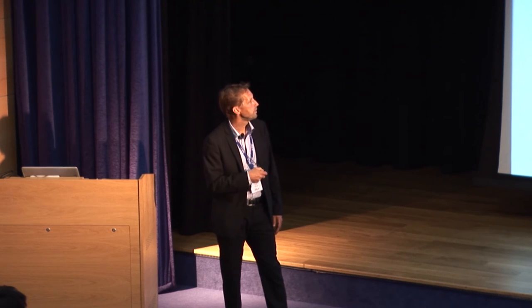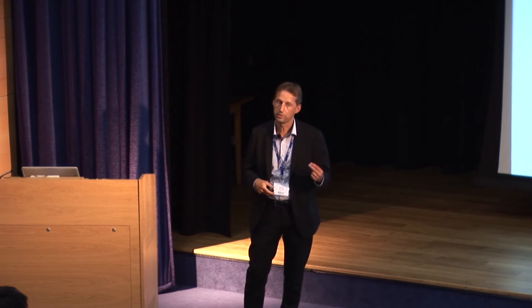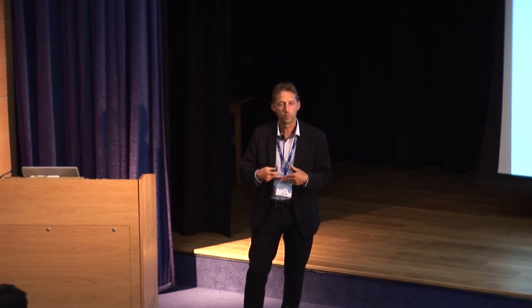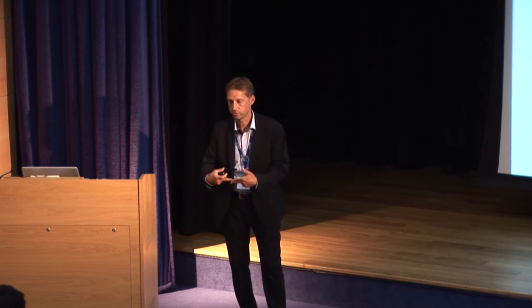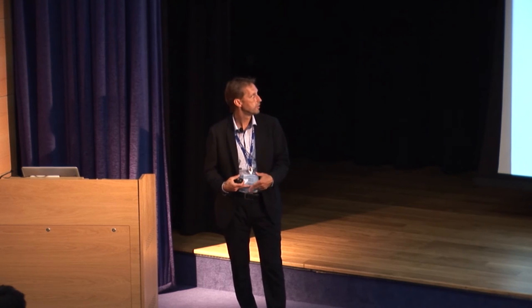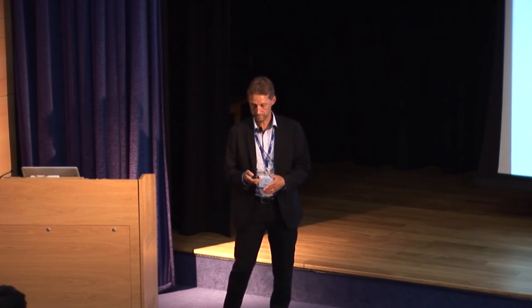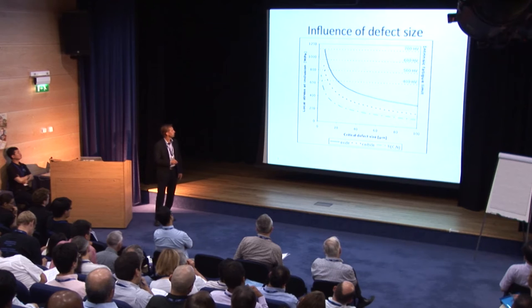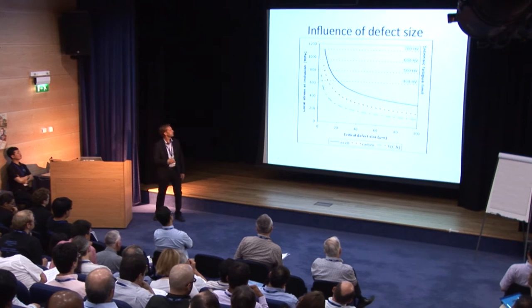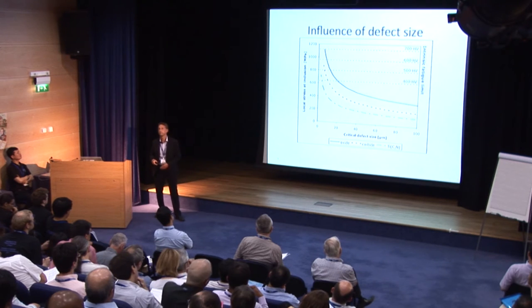For the oxides, we made a lot of tests. We have assessed all the fracture surfaces, calculating what was the smallest possible inclusion at the lowest possible stress that ever caused a fatigue failure. So it's thousands of samples that create that. For the carbides and the titanium, we should be a bit more careful. They are more fitted. But the oxide one, I feel quite comfortable with.